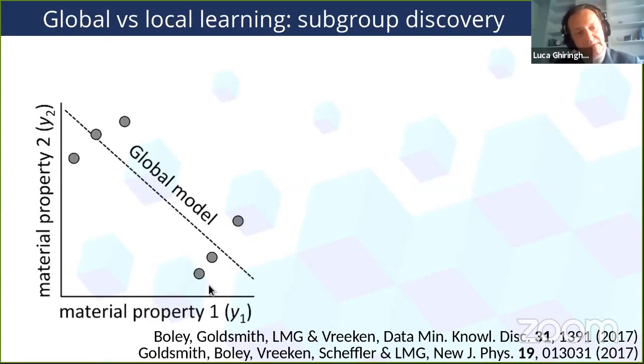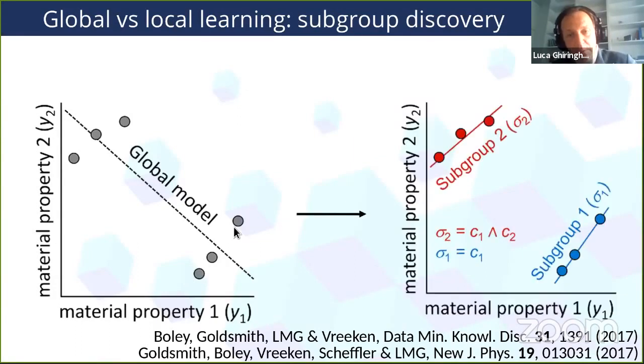And imagine that you plot these data points as property one versus property two, anything you like. You try to make a linear regression among these data points, and you see this kind of trend. But you also notice in this very simple case that if you split the data points into subgroups and you now do the linear fit, not only do you have a better agreement with the data points, but the trend of the local model is completely different from what happens to the global model. Now, again, think that this is just a cartoon. One would not do a linear fit with three data points and say this is better than with six.